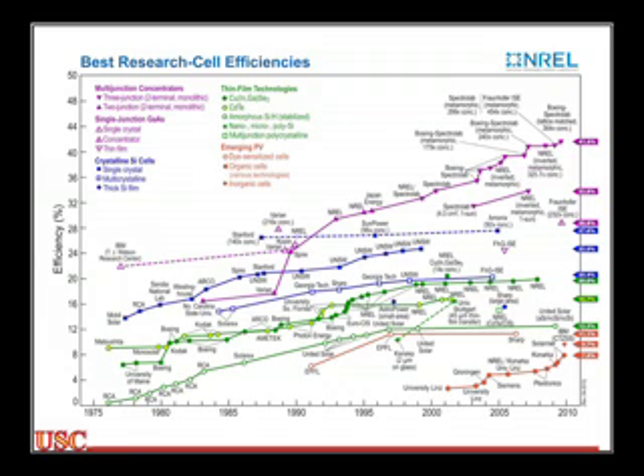So when I showed you those numbers, and we looked at the curves, and we had silicon solar cells that were putting out 27 and 28%, we're within 1 percentage point of the theoretical maximum. So when we were doing our work with OLEDs and getting into the 80s, 90s, even 95% range for efficiencies, that's the equivalent of 31% here, or 29% for silicon.